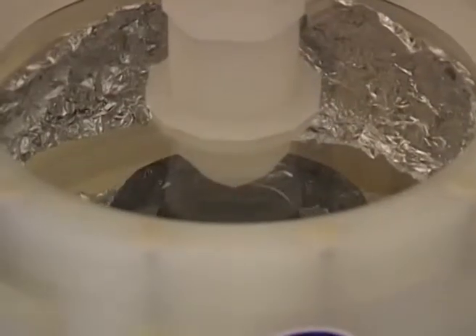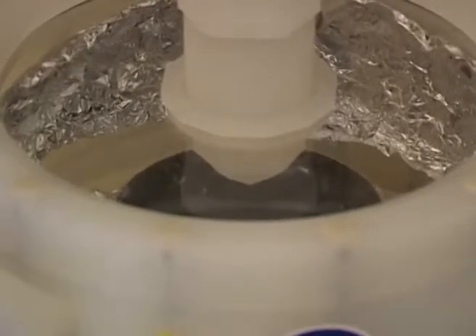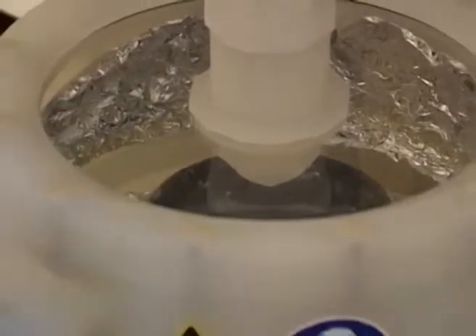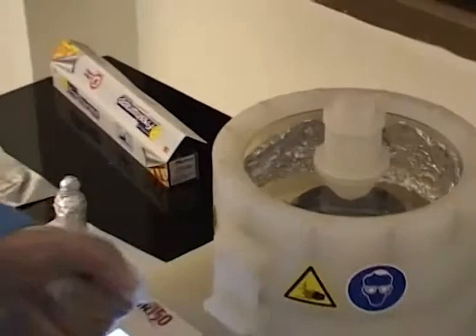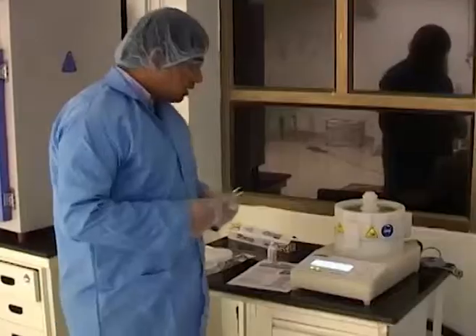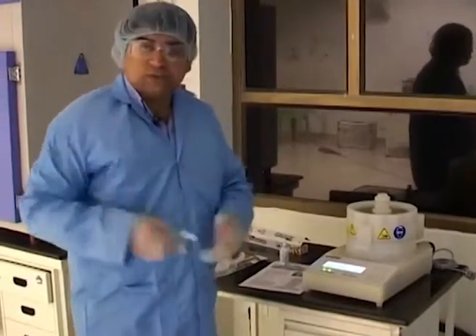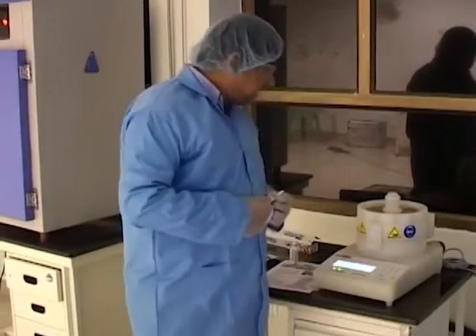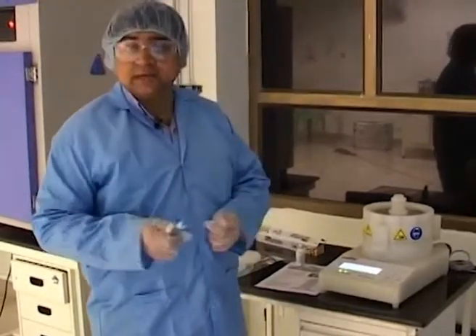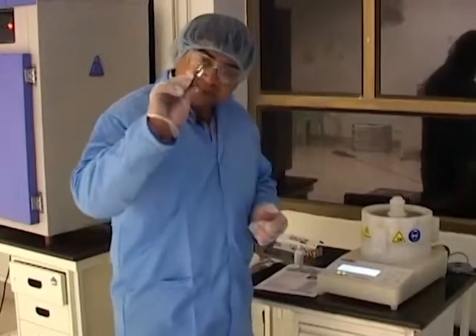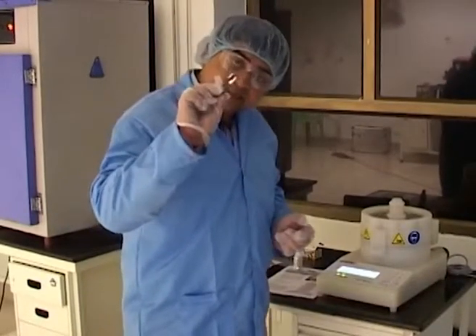Basically close this and just start the spin coating process, and let the film that we have set spread over the whole surface and create a thin film which is about 20 to 25 microns of this resist on the surface of the wafer. So now the resist is actually spin coated, and we have to be very careful about removing the wafer. We have to hold it from a thin corner at the sides, because that is typically the area where there should not be any designs and structures.